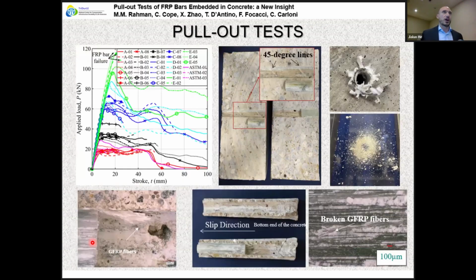So here you see the results. These bars slip inside the concrete, and the sand remains attached to the concrete and grooves the surface of the bar. You can see it here and also here. It leaves at the bottom of the specimen all the debris of the resin that is grooved by the sand.